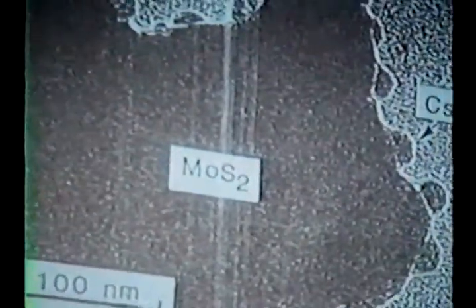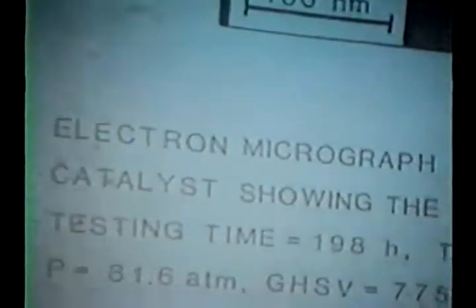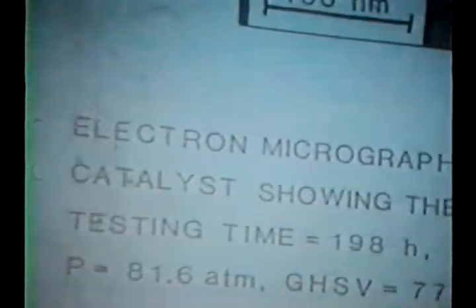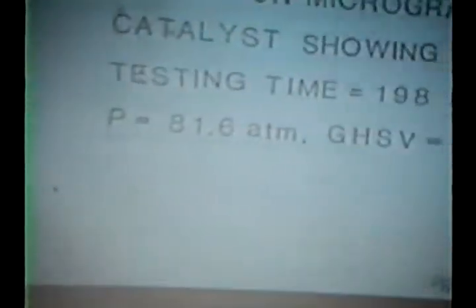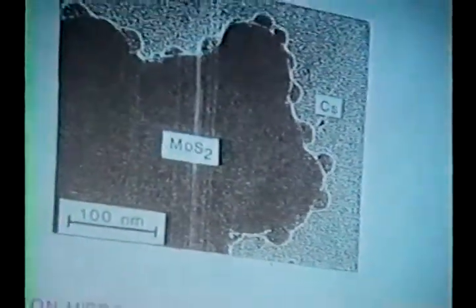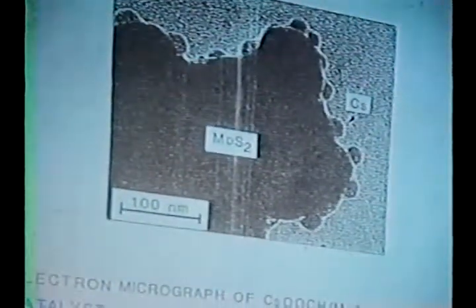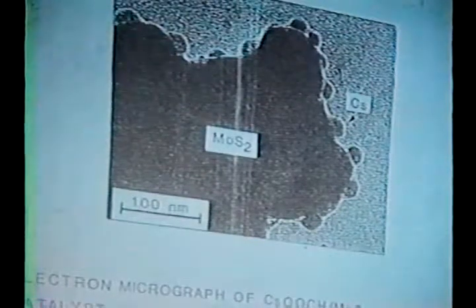And this is different from many other catalysts which are doped with alkali, in which the alkali compound disperses itself atomically in submonolayers. And much smaller concentrations of alkali are usually needed for producing maximum synthesis rate than in this case. The cesium particles are about 200 angstroms. They are sitting on what appears to be flat portions of the moly disulfide by forces that are weak, as weak as the surface energy of the moly disulfide. And no matter what you do to this system, you cannot prevent this agglomeration and clustering of cesium.